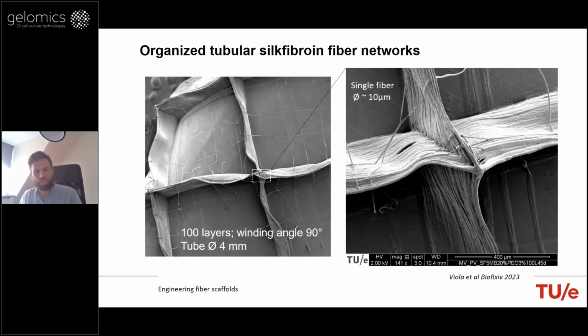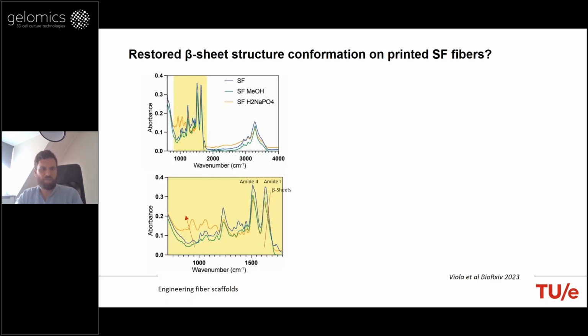So this was basically processing the silk with electrowriting, but one of the challenges was, of course, that these materials did not show significant restoring of the beta sheet structure. So basically what we did then was to investigate a post-processing treatment. In this case, we look at sodium phosphate, because it's known that in the presence of some ions, if you think of silk from spiders, when they lay down the silk in the spider ducts, silk molecules are exposed to different concentrations of ions, and that it's known to induce the cross-linking of silk.